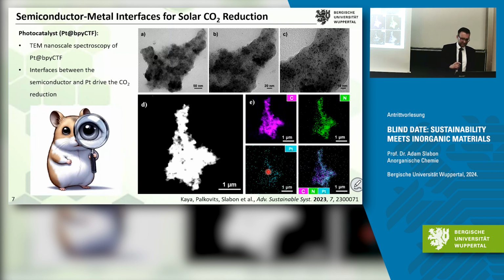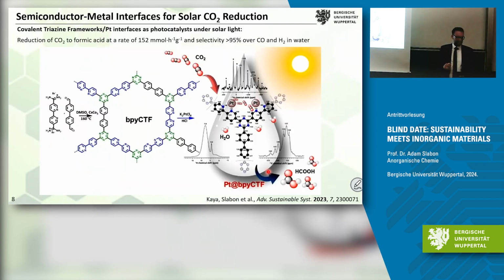Does the interface work? What we get actually is formic acid with 150 millimoles per hour per gram of catalyst, but we get a very high selectivity, over 95%, versus competing reactions like carbon monoxide formation and water. So we as chemists, we can design materials to get the higher performance.